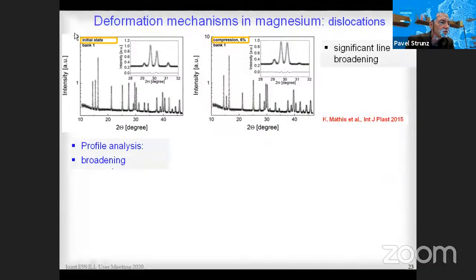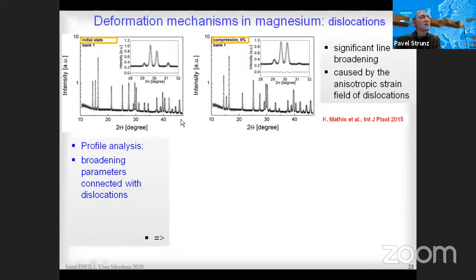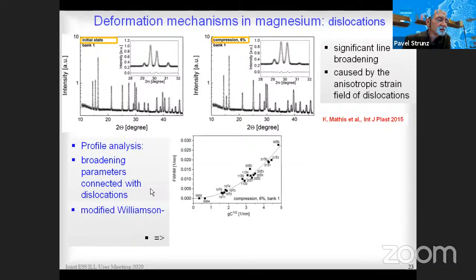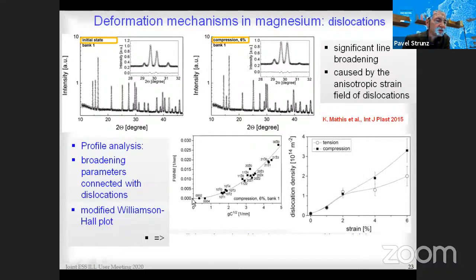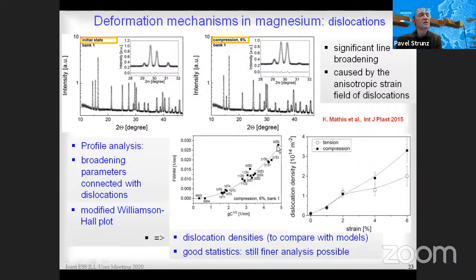Further, we can also use peak broadening for some other conclusions. We perform a profile analysis of the whole diffraction pattern with microstrain broadening parameters coming from dislocations. When we do it, we get again a modified Williamson-Hall plot, which tells us that our assumption about dislocation caused broadening was correct. And we can determine the dislocation densities again for larger strainings, different for tension and compression. Again, the parameter which can be compared with deformation mechanism models.